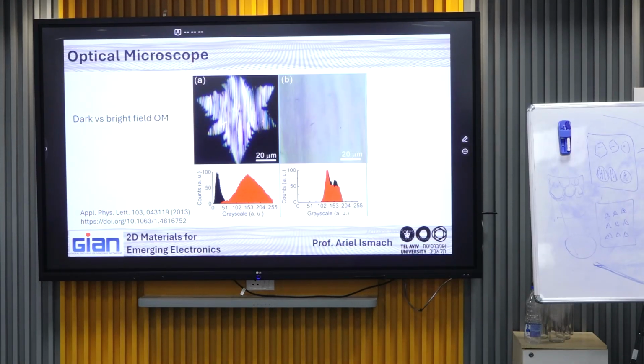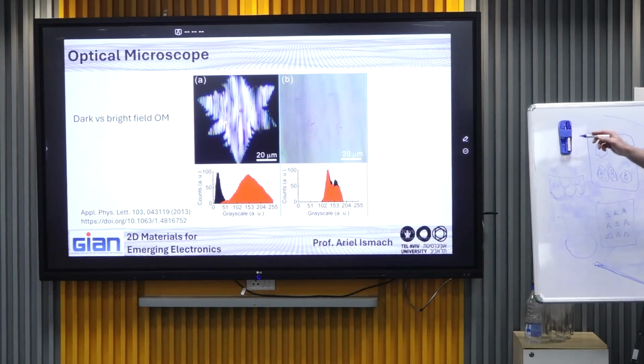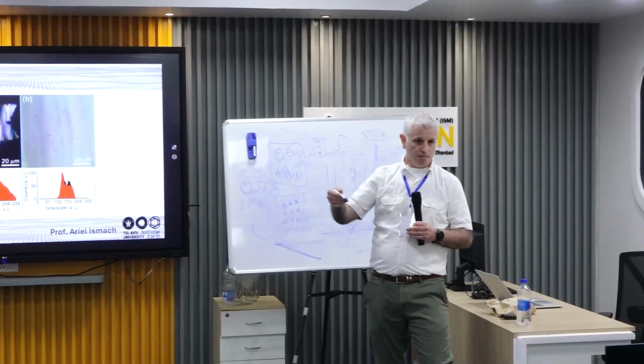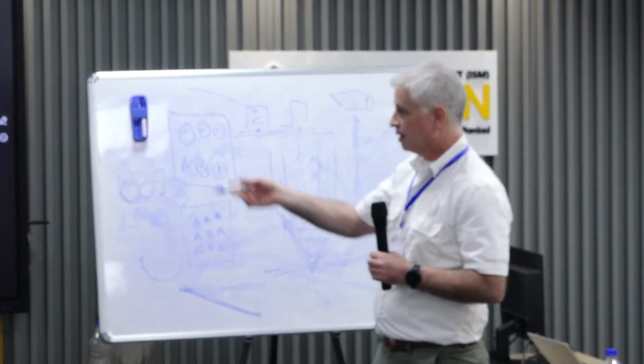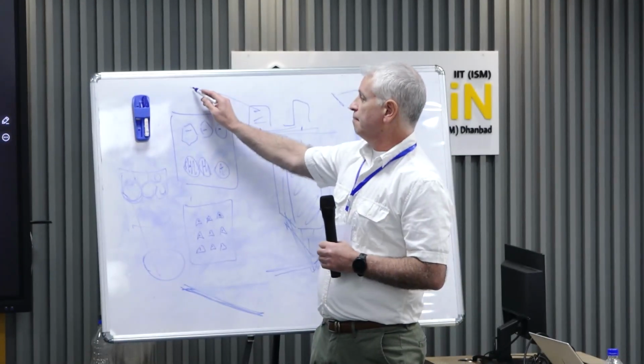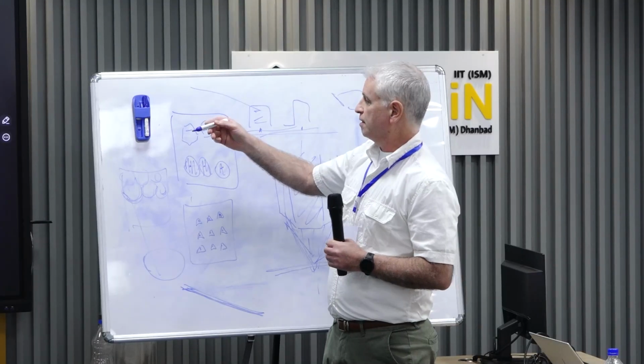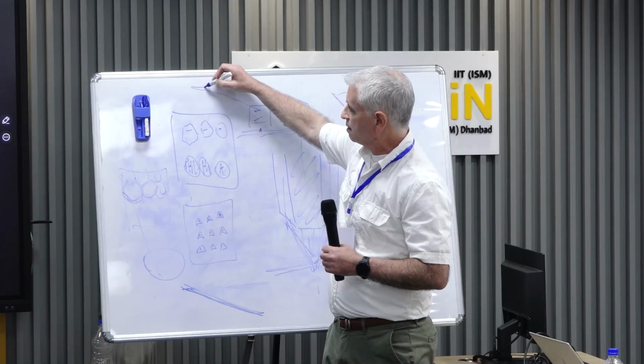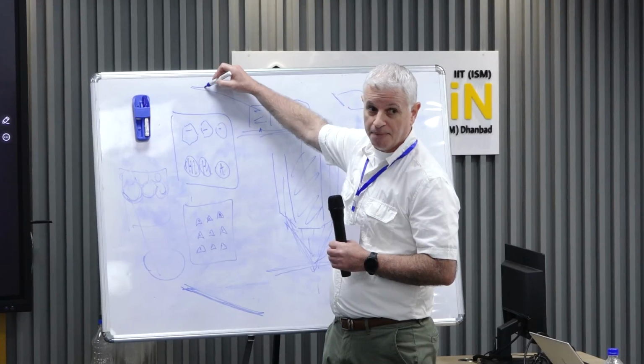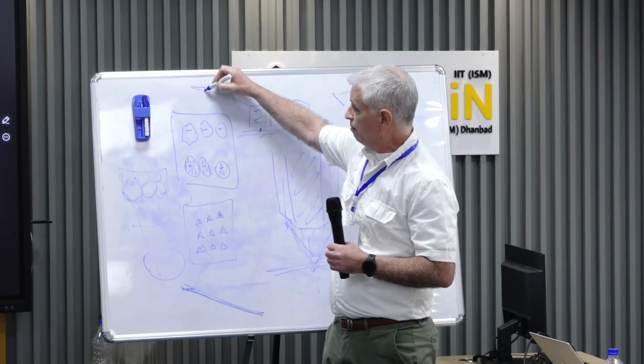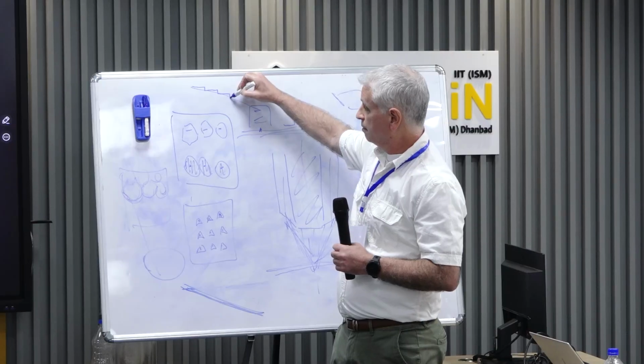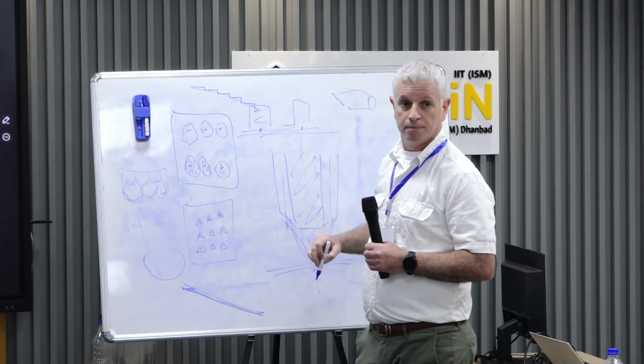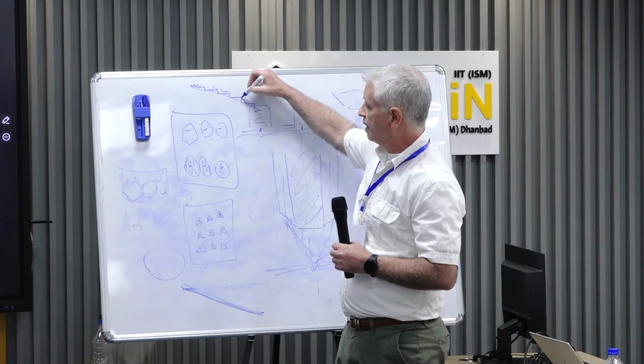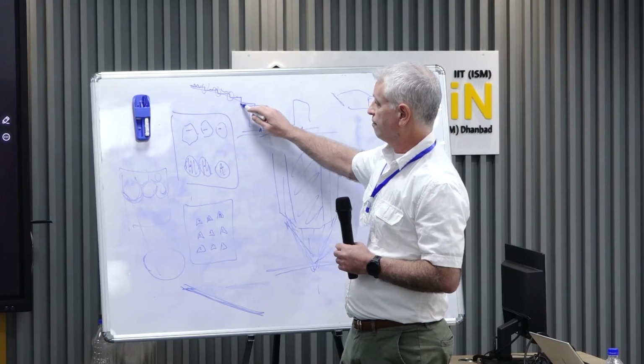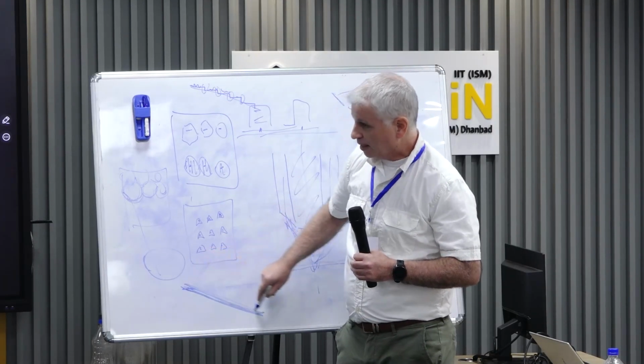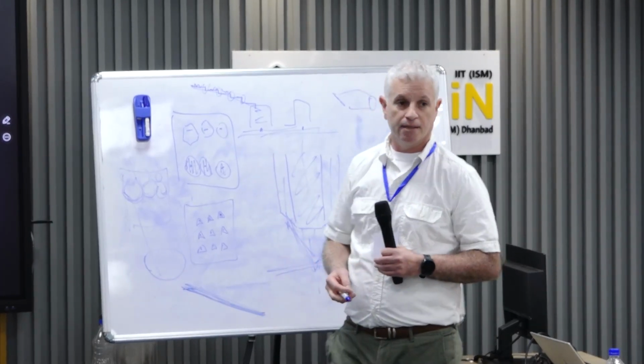So what the surface does in order to minimize the energy, especially when you do a heat treatment, you basically provide thermal energy, like in the case of graphene. The substrate tries to minimize the energy as much as possible, meaning that it tries to be at the low index plane as much as it can. But because of the miscut, it cannot be at the low index plane, and therefore steps or facets are formed. This area is low index, so low energy. But then you have these areas that are higher energy, of course. But overall, we reduce the energy of the surface compared to the high index plane, right?